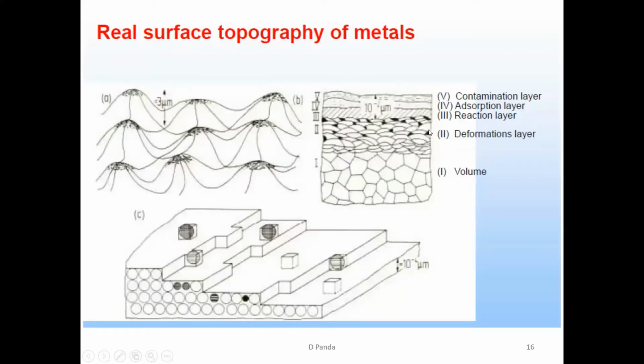So when we deposit some layer on the substrate, 5 parameters are very important. One is the volume of the substrate, and the second one is the deformation layer. Deformation layer means the top layer, just after the bulk. This layer will give you the surface tension or surface stress. If the surface stress and surface tension is much more, we can get different types of device stresses. And then the next layer is the reaction layer. The upper surface is the adsorption layer, where the atoms are. And sometimes that is the contamination layer.